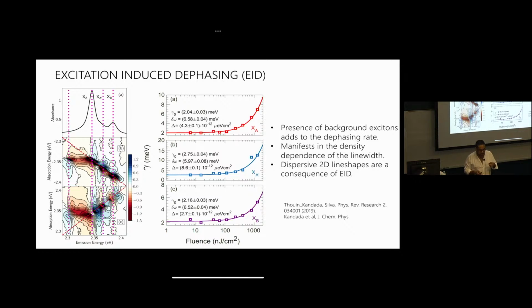There's going to be a low density limit where there will be a certain dephasing that will change between this sample or that sample, or Daniele's sample and Esteban's sample, or it got shipped by UPS from Milan packed in a prosciutto bag, but something went wrong. Literally, that's how they sent it to us. But something went wrong in Atlanta winter or summer, humidity and so on. So you get a different sample, and your dephasing at your low density limit is going to be different because the defect density is going to be different, and scattering sources are going to be different. But let's say that that's your gamma zero.